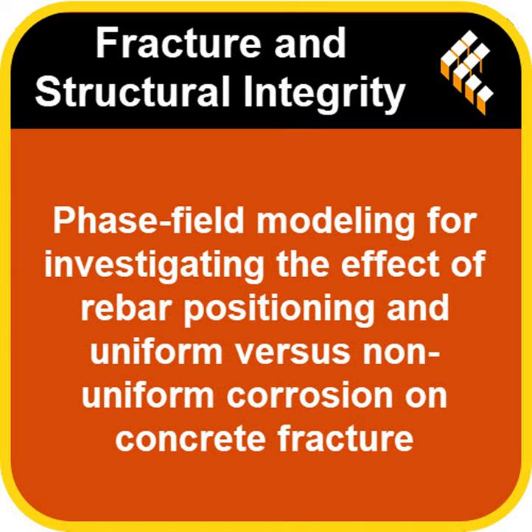But they also started seeing additional cracks, sort of branching off along the edges of the concrete section, more complex patterns. Okay, so potentially more widespread damage. Potentially, yes. And importantly, the amount of rust expansion needed at T1 to start the cracks and T2 to get them to the surface was actually larger than in the uniform case for these arrangements.